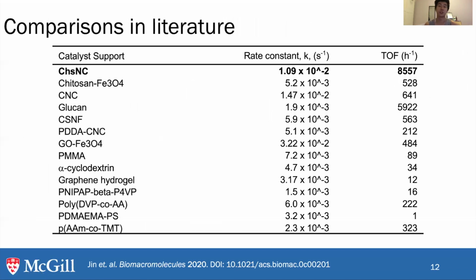So for the comparison with the literature, we're comparing this first and foremost with cellulose nanocrystals as the catalyst support, for all gold nanoparticles. And you can see that it blows everything out of the water in terms of turnover frequency number. And we can see that even with graphene and cyclodextrin, carbon-based biopolymers, it blows everything out. So the unique chitosan nanocrystal amine functionality, as well as its nanocrystalline domain, really spurs it on to become a great catalyst support.